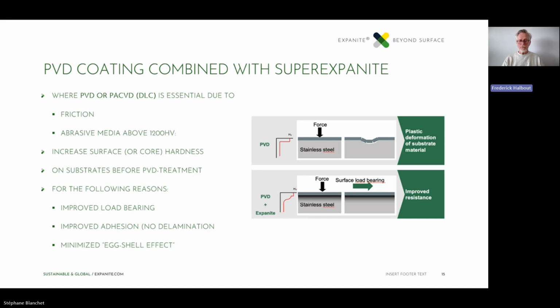So if you do an Expanite before the PVD, you have an increased hardness on the surface on which you can put an even harder coating on top. Illustrated as if you take a pane of glass and put it on a mattress and stand on it, it will break. But if you put between the mattress and the pane of glass a bit of plywood or something, you should be able to stand on it. That's the general idea. So you get a better load bearing for the material, so that it can withstand impact much better. And choosing Expanite for this is of course to maintain the corrosion resistance in the material, because as Stefan also said, it's a highly corrosive environment where these ball sectors are.